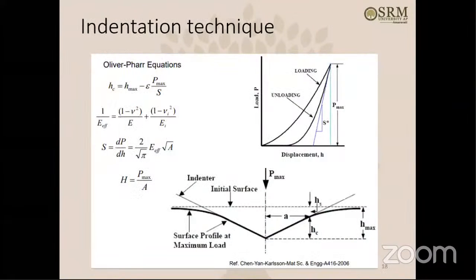So what is the indentation technique? There is a scientist called Oliver and another scientist called Pharr, and they developed these equations. What do the equations mean here? If you look at this indentation sectional plot, you can see the indenter coming from the top, and it is creating that impression there, like a valley. This is the nomenclature of that valley. When the indenter puts pressure on the surface, it creates a valley like this. If it's a conical indenter, it creates a conical valley like this.